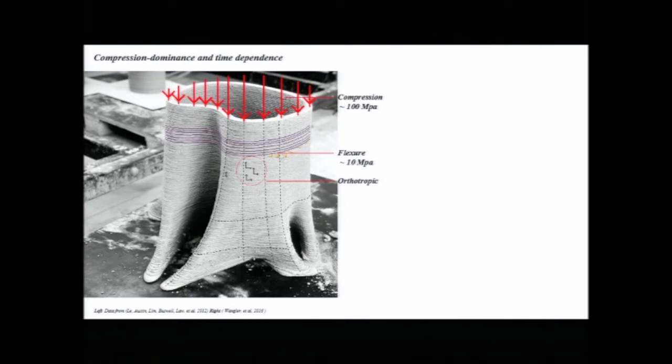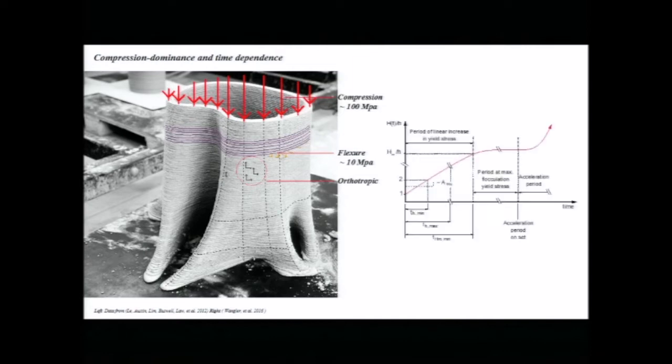It is very high in compressive strength, relatively low in flexural strength, and the unique things that the research also has to address are that there's a peculiar orthotropic behavior to printed concrete, and the other main thing the research and approach has to address is the time-based hardening of the material, which is usually not addressed in the design phase of masonry structures.